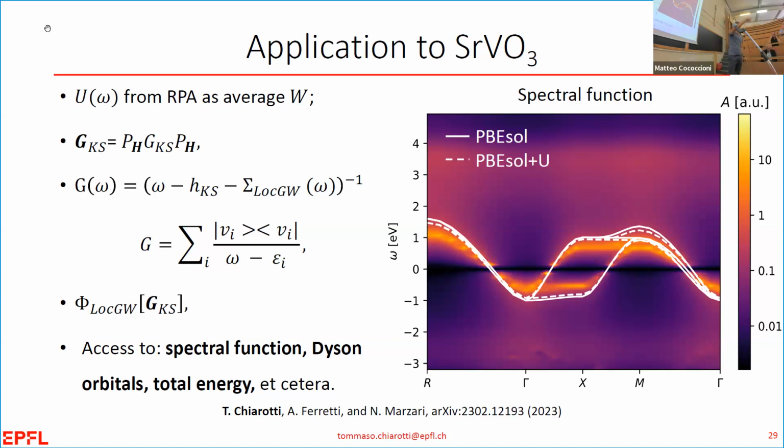In insulators, in which DFT plus U works better, it works exactly as DFT plus U. It takes the t2g band and opens the gap exactly the same way that DFT plus U does. So in some sense, there is no contradiction. There you wanted to fix the curvature; here instead, you add the screening. And in physics, same result, because it's the correct one.